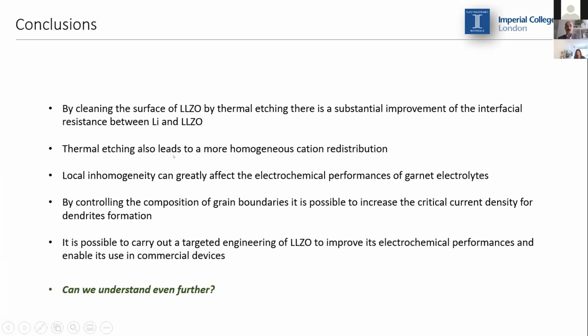We also see how local inhomogeneity can affect the electrochemical performances of garnet electrolyte and how they can have an effect on the activation energy of grain boundaries. And by playing with the amount of cation at the grain boundaries, we can actually tune the critical current density for dendrite formation, and in that way do a targeted engineering of materials.